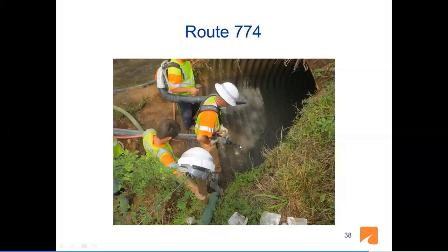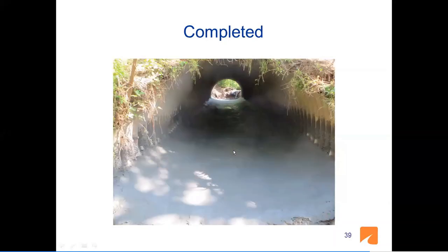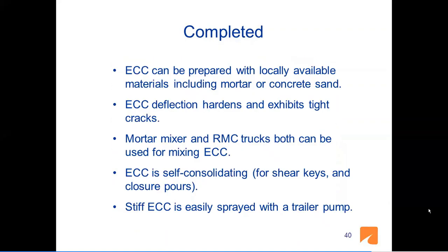And then, as you see, they are spraying. And it sprayed well, it stuck well, and it didn't flow on the side. So they were happier with the stiffer ECC mix. And the completed culvert, as you see here, looks very nice. And these culverts went through very high flooding and very heavy rains, and they seem to be performing well.